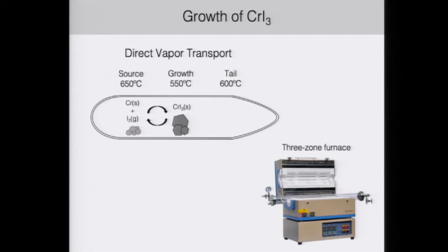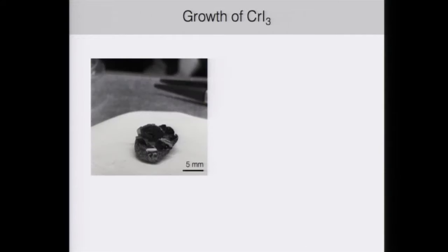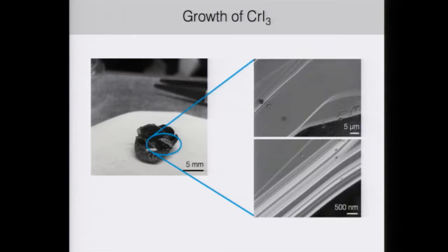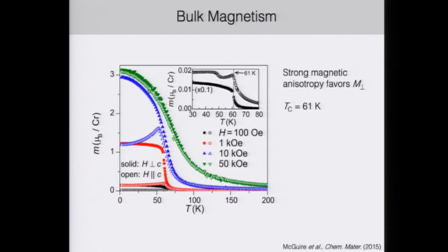So we can grow chromium triiodide by the direct vapor transport method, which is a type of chemical vapor transport. So we place chromium and iodine inside a sealed evacuated ampule, and then we place it in a 3-zone furnace where we assign a temperature gradient that gives rise to vapor transport that ultimately nucleates and results in chromium triiodide crystals. These crystals are rather platelet-like, and as you zoom in further and further along the edge of one of these crystals using scanning electron microscopy, you can see that it looks almost like the pages on the side of a book coming apart. So this is highly suggestive of an exfoliatable material that has a strong van der Waals character. The bulk magnetism has been previously studied and shows a strong magnetic anisotropy favoring the out-of-plane axis.